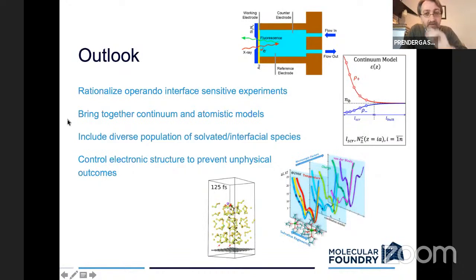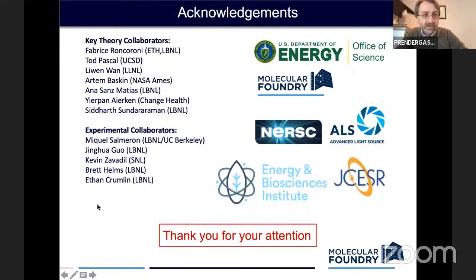So the outlook from all of this, if I had to summarize it, is that yes, there are some very nice experiments out there that we'd love to rationalize. There are different techniques that we need to bring together, I think, to do this well. And so we can definitely learn a lot from continuum models and use those to inspire atomistic simulations, and then to do that self-consistently. We're realizing with some horror that there's a very diverse population of species in some of these solutions, and we need to take care of that carefully, especially at the interface. Free energy sampling is helping a lot there. And then we also need to be careful about our electronic structure as well, that when we model these electrified systems, there are some outcomes that might be unphysical, and we need to mitigate against that by putting in the proper constraints.